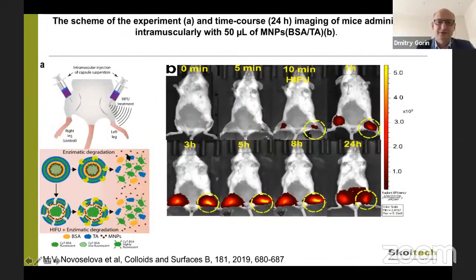And here you can see the results where we injected shells that contain encapsulated dye, and gold and magnetite nanoparticles that can also quench our fluorescence dye. We injected this suspension into mouse legs, and then irradiated one leg with high intensity focused ultrasound. And you see, we have degradation in both legs, but where we destroyed our capsules beforehand by ultrasound, we can see an increase of fluorescence. And this is a very important result.